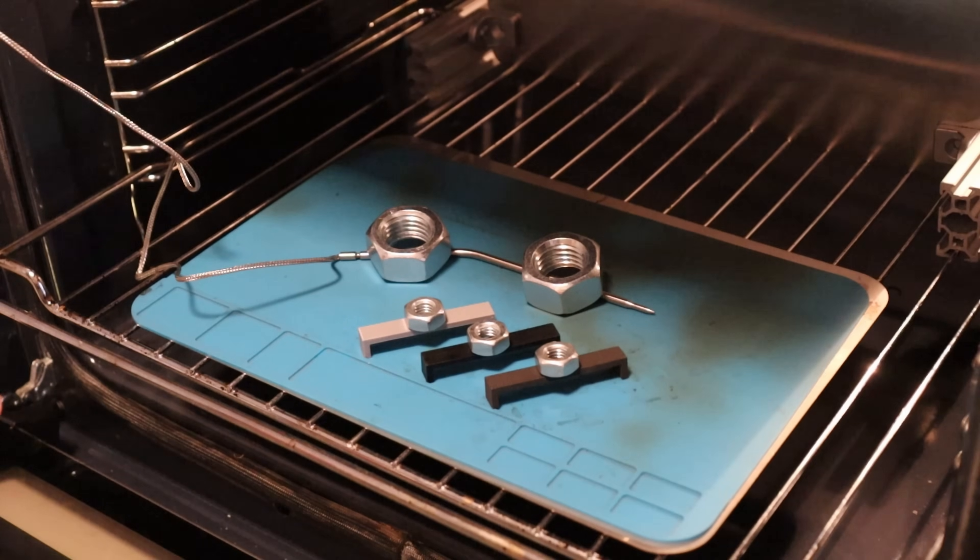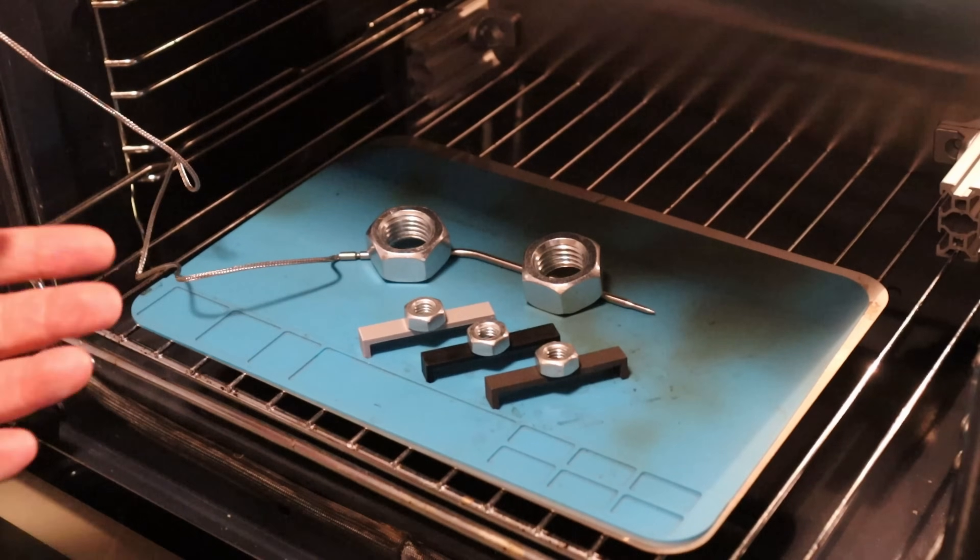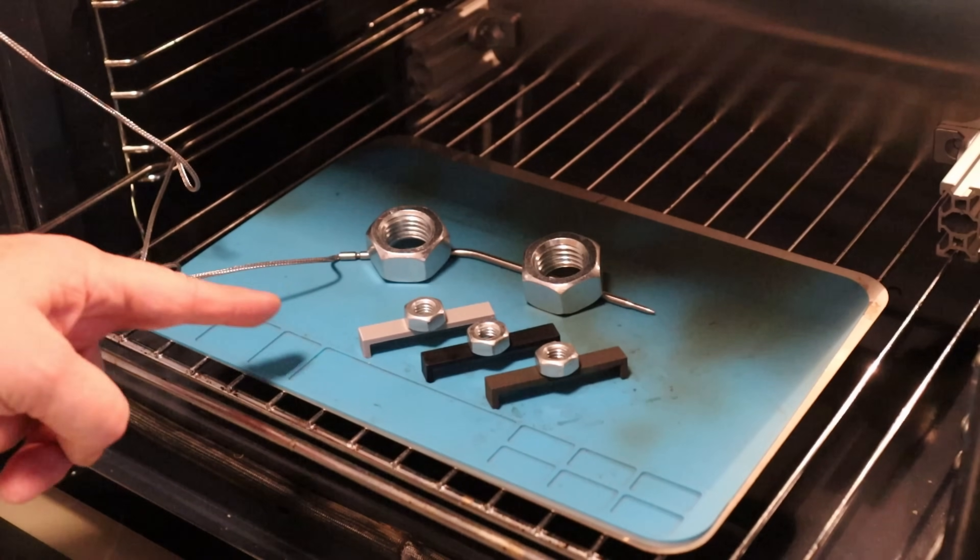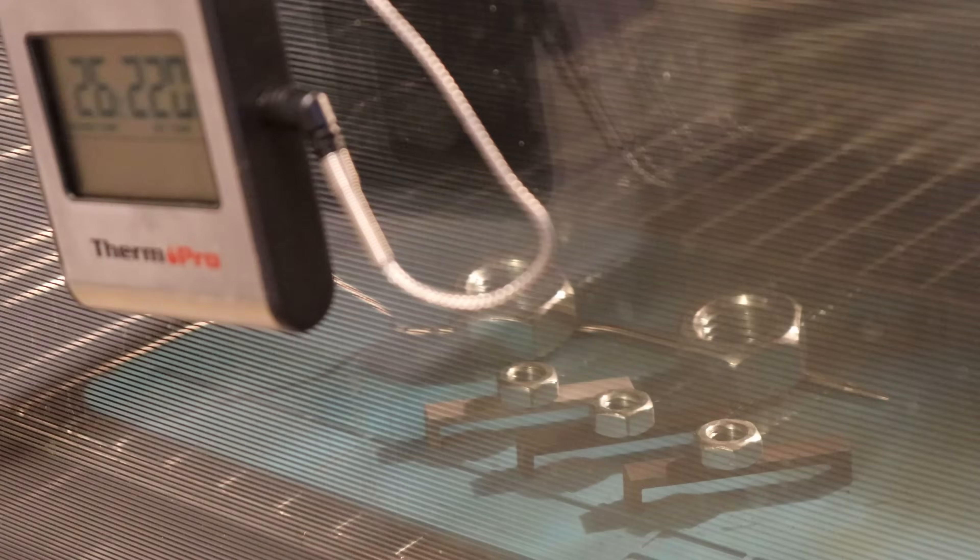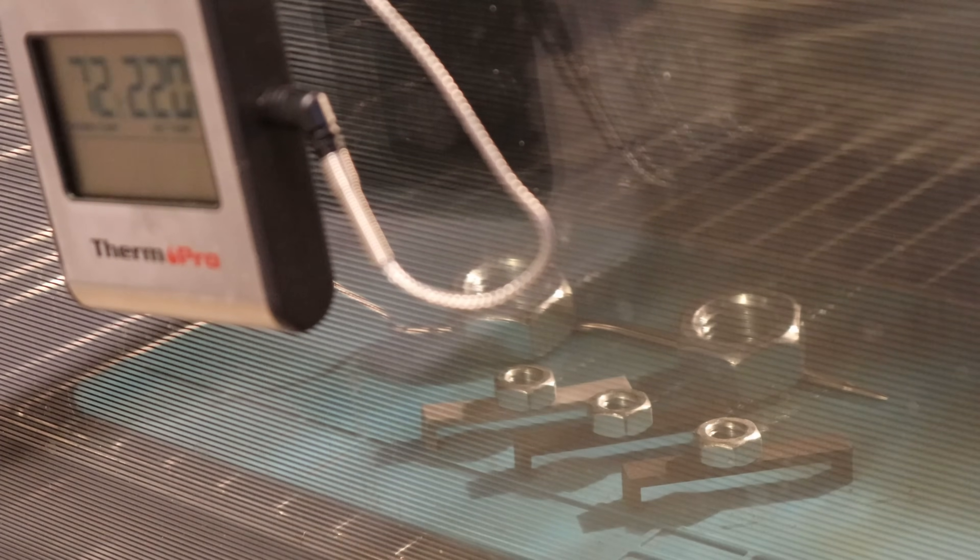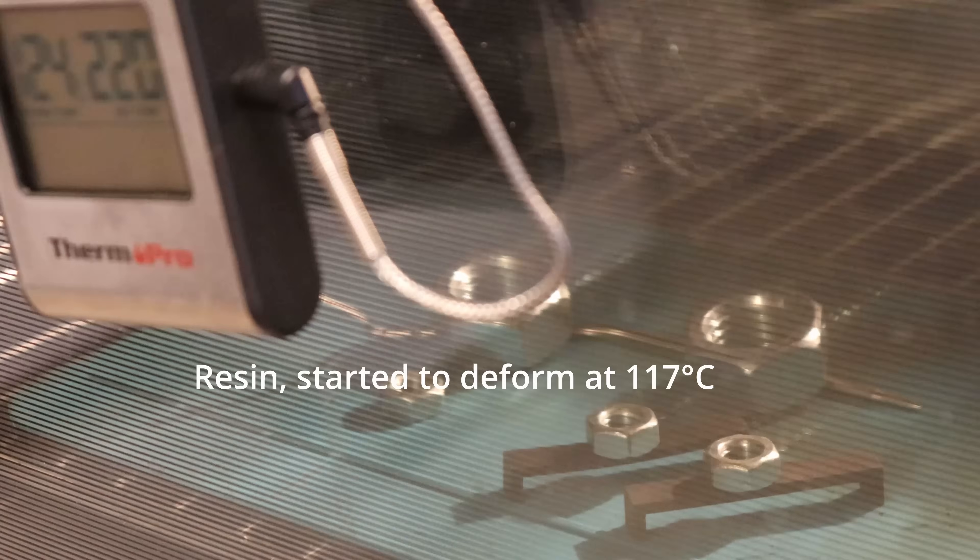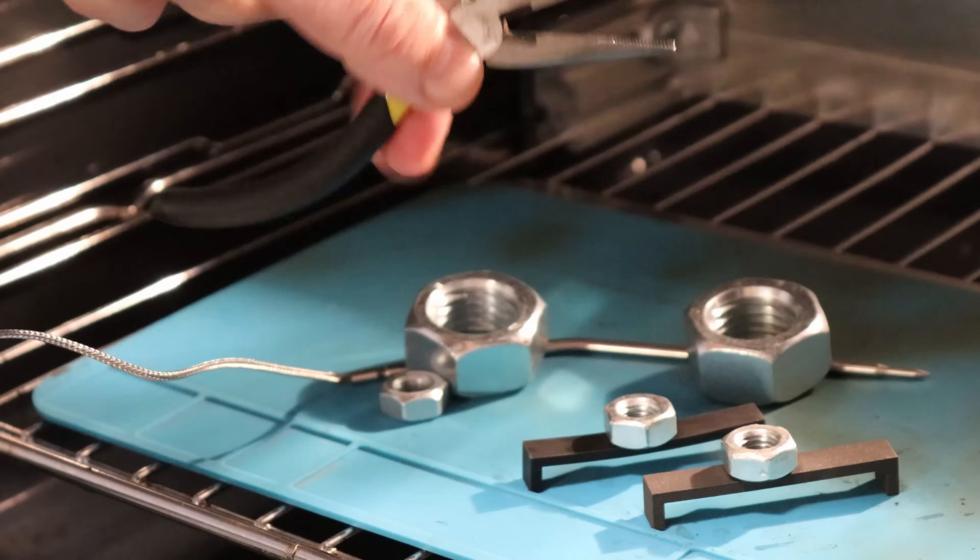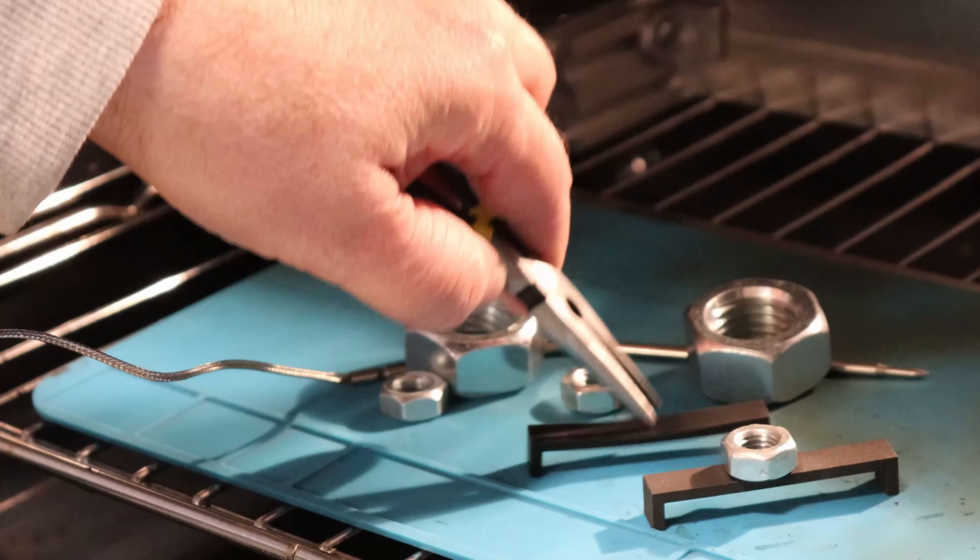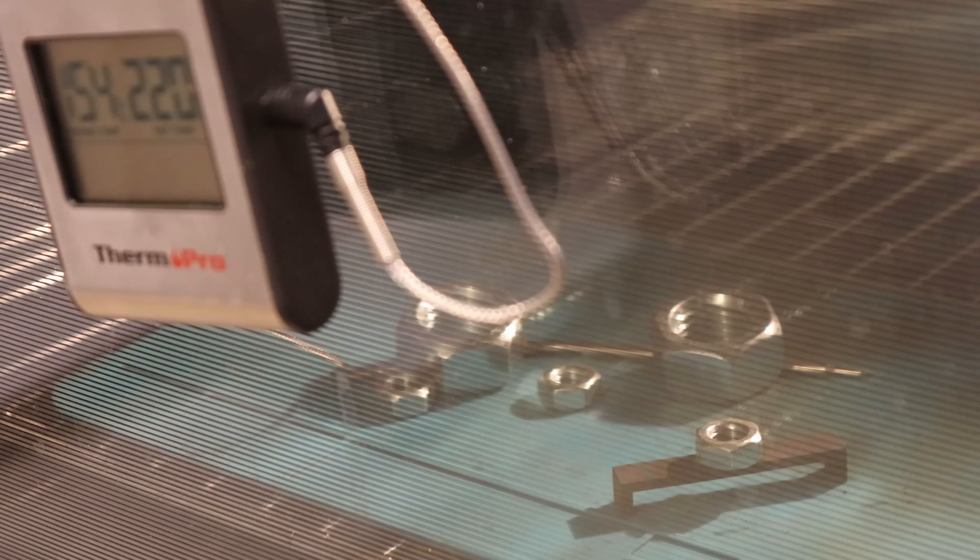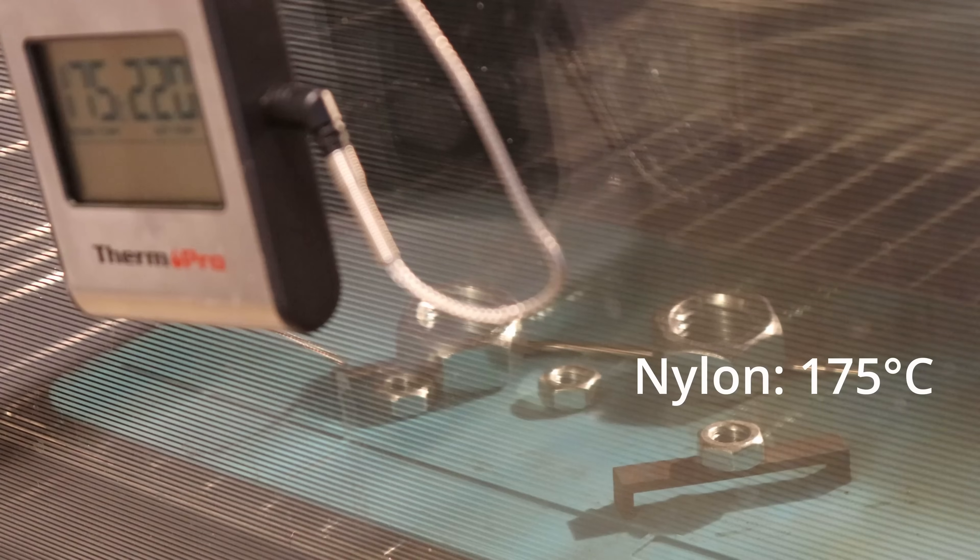Temperature test in the oven and if the resin will start to deform really so early I have to take it out because with the nylon I will go much higher. And also I have these test objects from the TPU for comparison. This is a speed up timelapse video and this TPU started with deformation quite early so I took it out earlier and the first deformation on resin I noticed on 117 degrees celsius. 124 degrees celsius and I can see some small deformation on the resin, I want to see how hard is it. Soft. Yes this is very soft now and I will take it out.